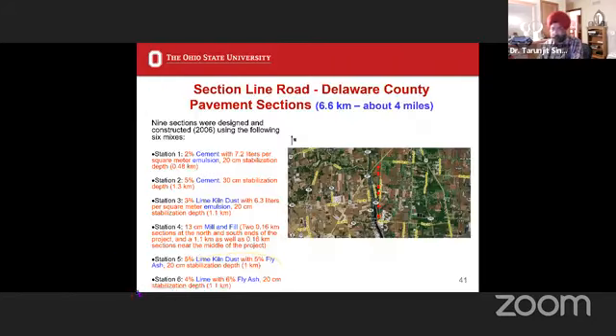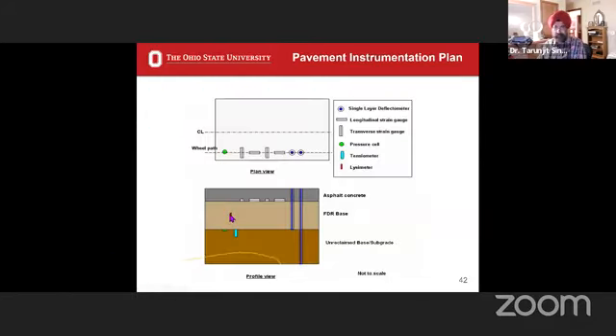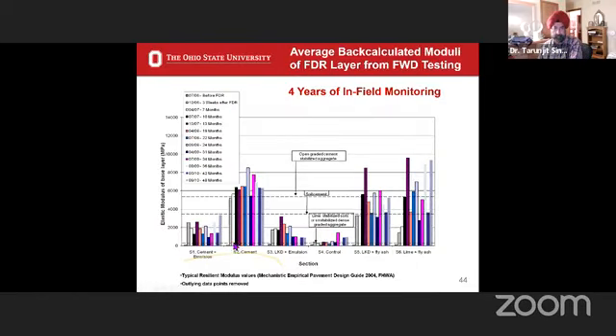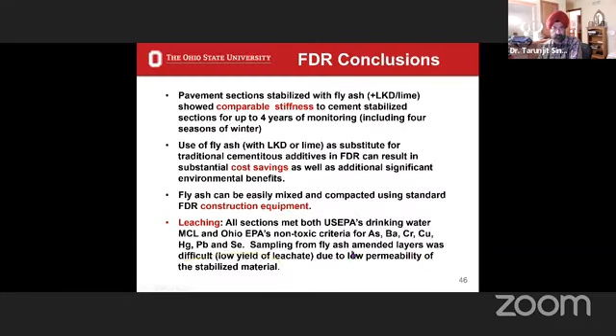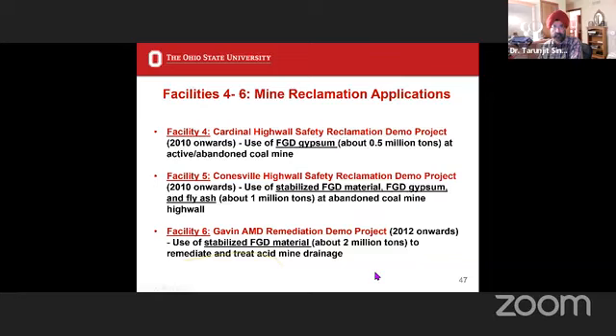One interesting thing you found, if you see here, I talked about this lysimeter, right? The permeability of this base for our cement and fly ash, lime, and LKD was so low that we hardly could get water out of it, because you would suck water out of the pore space. So the permeability of this base layer was so much lower for the cement, LKD and fly ash, and lime and fly ash mixes that we had. I talked about very low permeability.